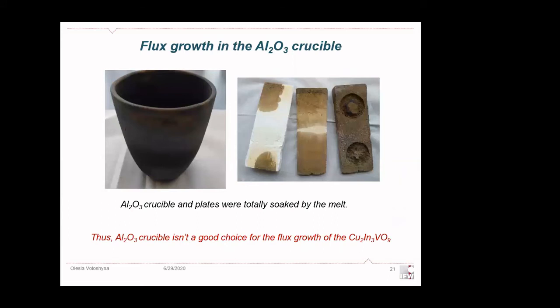And as you can see, after the experiment, as it was carried out in an alumina oxide crucible, all the crucible and even the plates that were situated under the crucible were totally soaked with the flux, and it means that such crucibles are not sufficient for such experiments.